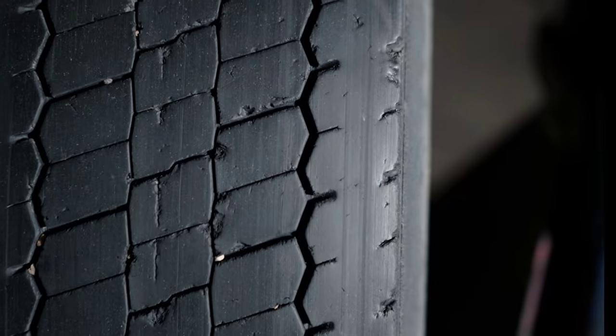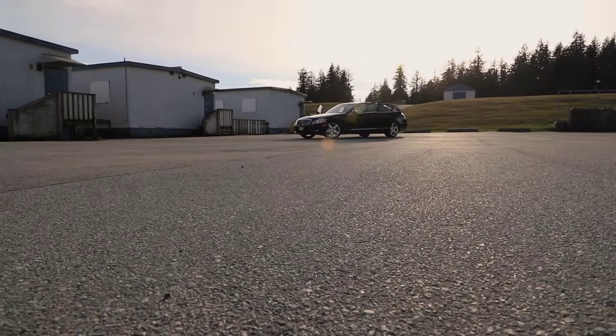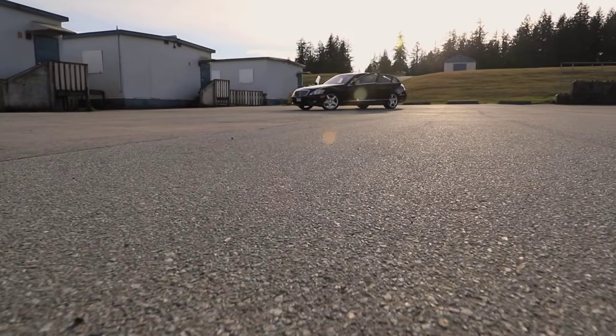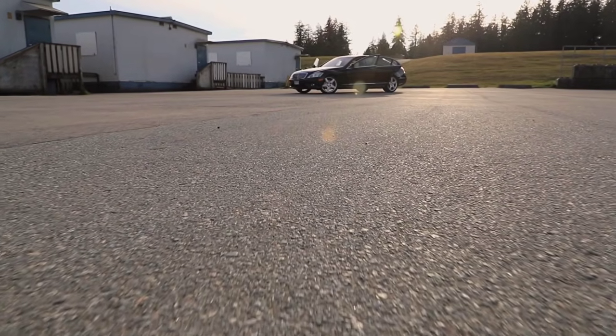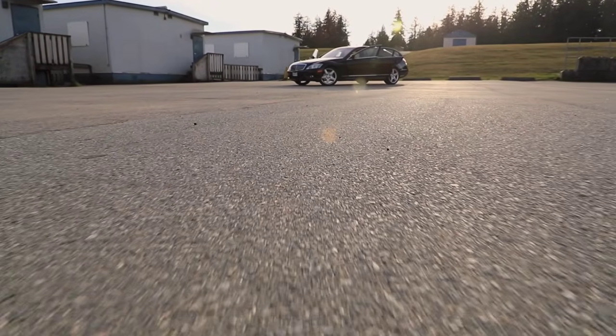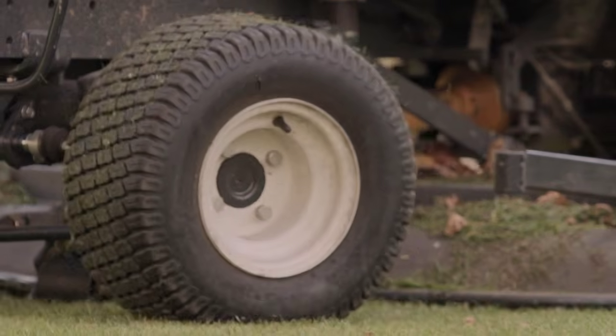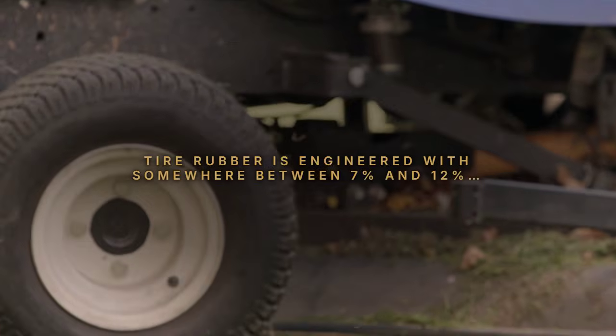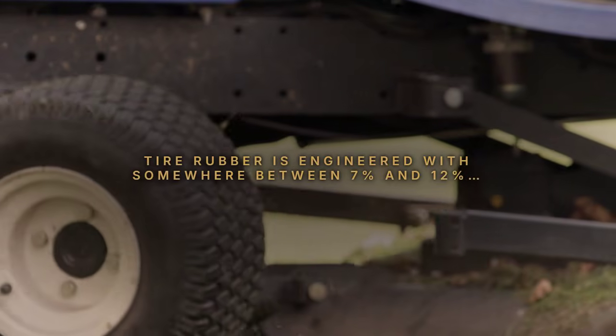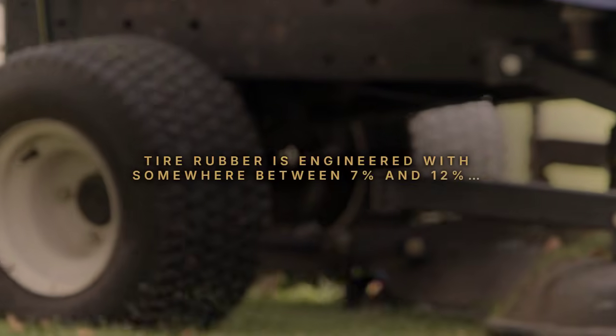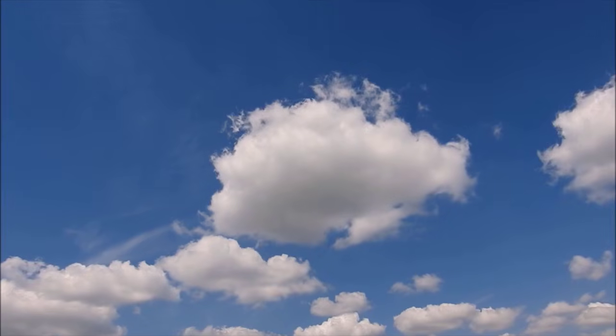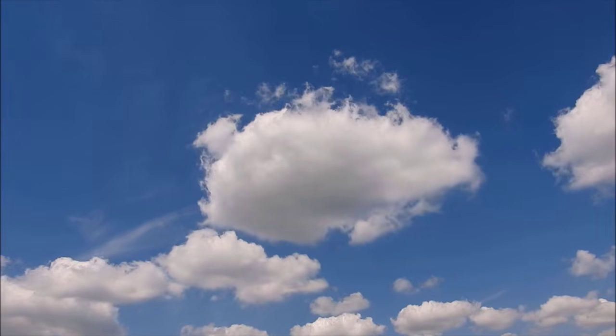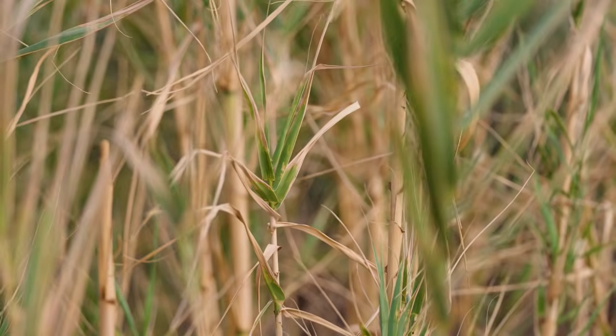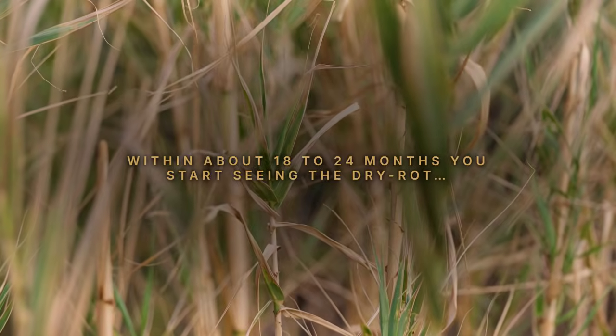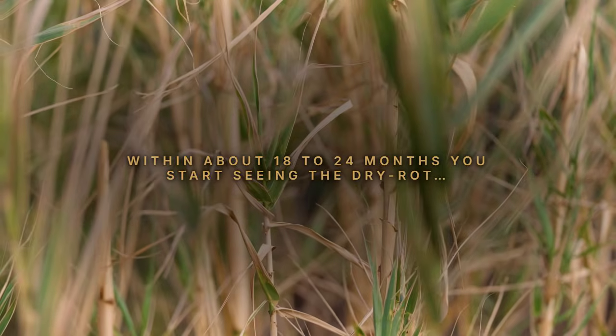But here is what is actually happening under the surface. Most commercial tire shines are silicone or solvent based, and those solvents pull the natural oils right out of the rubber. Tire rubber is engineered with somewhere between 7% and 12% plasticizing oils baked into the compound to keep it flexible. When you spray a solvent-heavy shine on it week after week, you are leaching those oils out. Within about 18 to 24 months, you start seeing the dry rot cracks crawling across the sidewall.